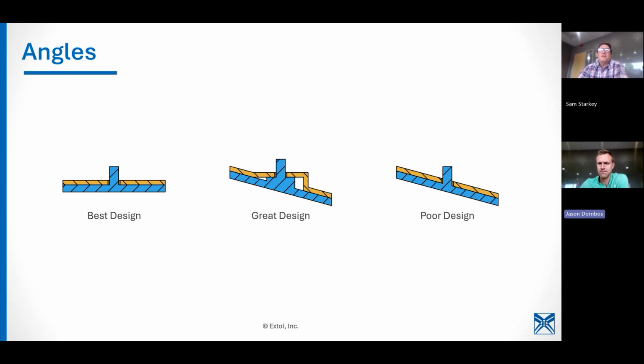So in this case, the only way we would be able to get around that is by angling the boss cut into the punch. And so it starts to create problems where it wants to kick out and slide. It's like a little ramp that they're going to go down. Yeah. You'll start to see some shifting where that final head is related to the center of that boss. So you'll start to get some shifting, very inconsistent results as far as strength goes. So if at all possible, try to design to the left one and not the right.